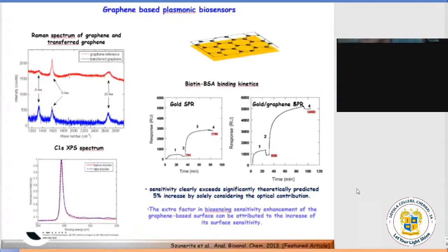And now when we transfer that to gold, you see the D line increases slightly because you actually transfer from copper or nickel to gold. This mismatch is not the same. So indeed, you generate more defects on the graphene layer. However, if you look at the XPS spectrum of the carbon, it's really clean. Before and after transfer, there is no impurity, as I said before, when you use this Scotch tape.